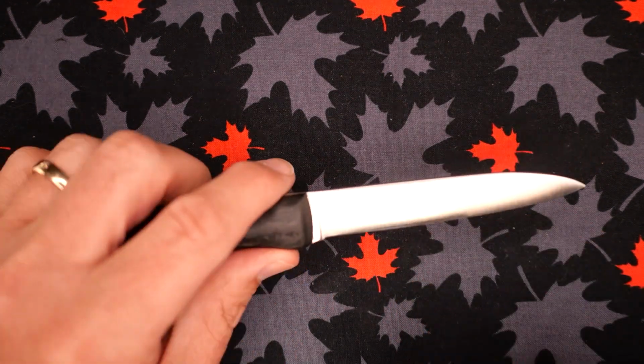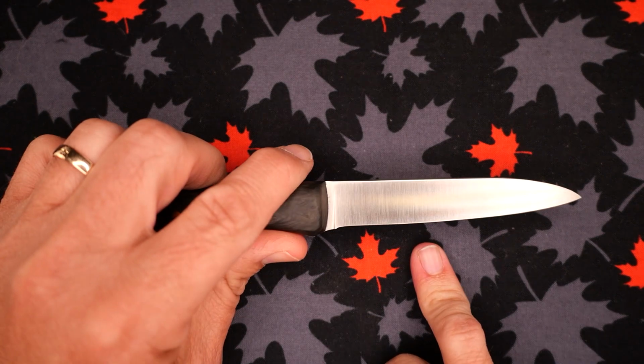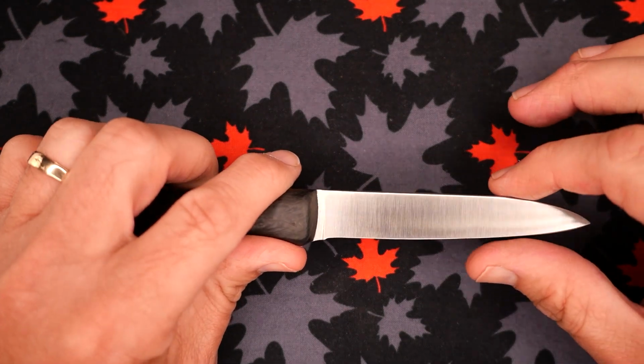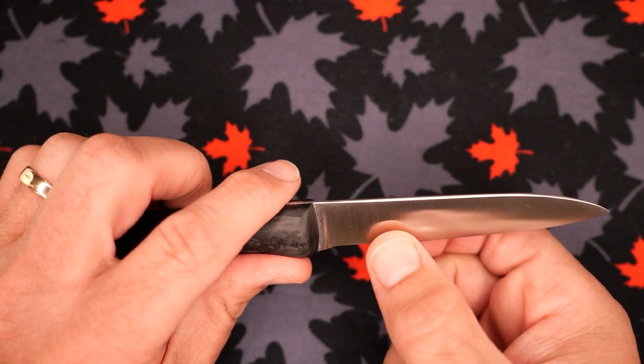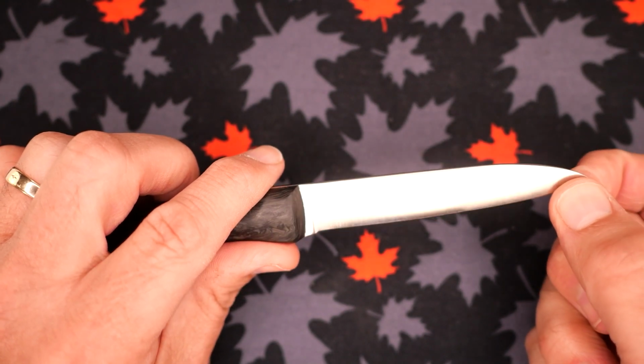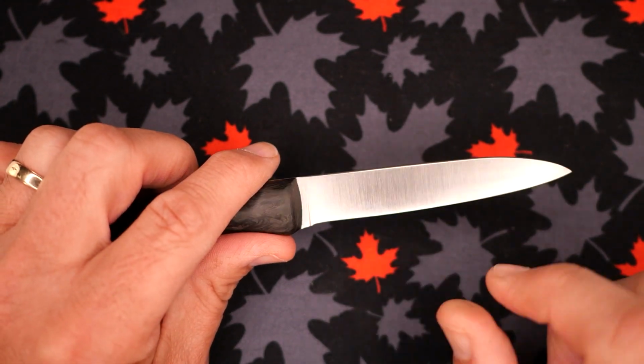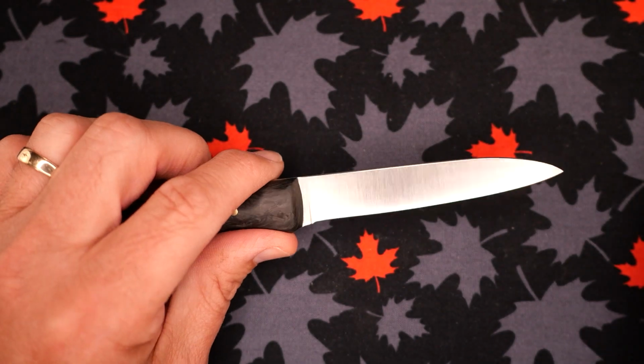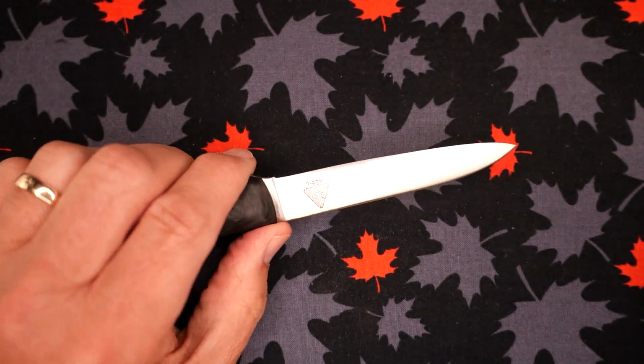How thick is it right behind the edge grind? 0.2 millimeters, 8 thousandths of an inch at the thinnest spot, and over here it's about 10 thousandths of an inch, closer to the tip. No wonder it's so very, very slicey indeed.